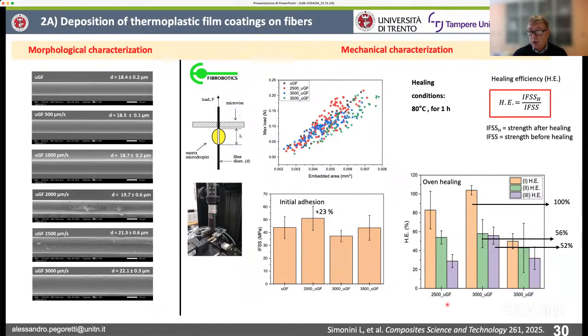Here you can see for basically the conditions that we at the end selected, you can reach an increase. Basically, sorry, this is already the healing efficiency reported. So you can see that the healing efficiency is quite high. And here you can see 3 bars because we healed the interface 3 times consecutively. So we broke the interface once, then the second time, and a third time. So you can see 3 different values. The first value is the highest in general, so we can reach also values which are around 100%, so we can fully restore the initial adhesion.